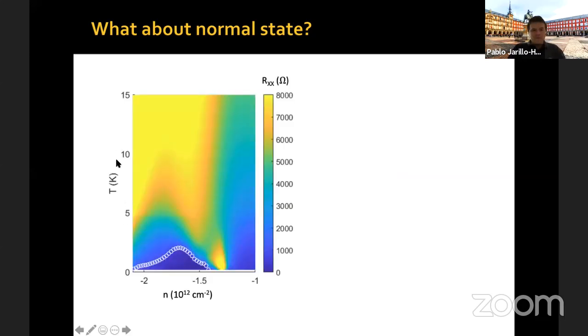Let me go back to the normal state. So we have, again, this phase diagram, temperature versus density. We have the superconducting dome. We have the correlated insulating state for 2 holes per moiré unit cell. We have this resistance wedge, with a depletion of Tc there. Now, these are measurements in the color scale. This is a measurement of the longitudinal resistivity. What happens if I take measurements of the transverse resistivity? So the equivalent of doing a Hall measurement, but at zero magnetic field, no magnetic field applied.